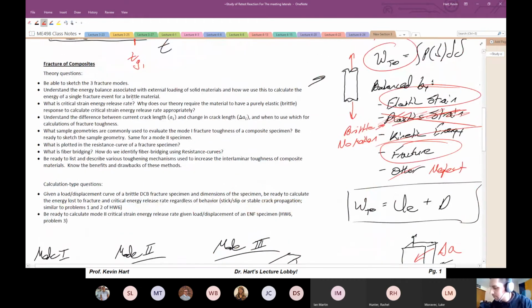So what is critical strain energy release rate? Well, I just talked about that. Why does our theory require the property to be purely elastic in response to critical strain energy release rate appropriately? So we talked about it being brittle because we know that it has to be just elastic strain and fracture that balance this thing out. So we have to have brittle behavior so that we can eliminate plasticity. So brittle, no motion, eliminate plasticity, eliminate kinetic energy. So that's why our theory requires the material to have a purely elastic response.